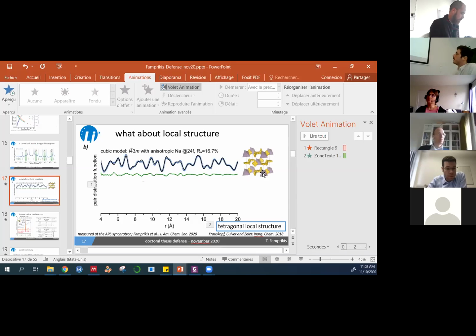Yeah. Now, I always believe experiments, much less DFT, even the DFT that we do ourselves. But when we do DFT on these cubic structures, and we put the sodium on this 24F site, it just immediately relaxes towards the, what is it, the 6B site. Oh, yes. This is not necessarily surprising, in the sense that you can see that the 24F is simply an anisotropic extension, if you will, of the 6B site, right? So what we're explaining here is not necessarily where the stable position is. What we're explaining through such a model is basically the mobility of the sodium parallel to the axis. Right, to the diffusion pathway. Yeah. So this is really what you're seeing here, not necessarily that the stable position is always going to be the 6B. Okay.